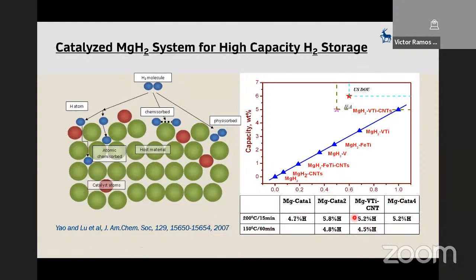So we have developed systems that, with the catalyst around here, give you almost 5% capacity, and the desorption temperature within 60 minutes. This is within 15 minutes is 5.2%, at 200 degrees C, but at 150 it will take longer. So this is still not ideal, but it's getting very close to the DOE target.